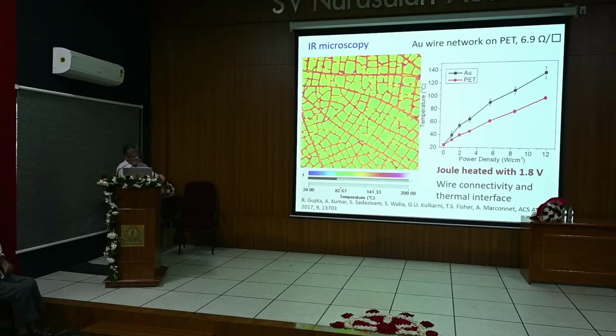And I can use this wire system and pass a little current. When I pass the current, because it has electrical resistance, it heats up, and I can record it with IR camera, IR microscopy, and these are the actual wires here, which are sort of hot. Actually, they are quite red hot. They are around 140 degrees centigrade or so. You can go on increasing the temperature, play with it and all that. You can study the thermal property of these systems.